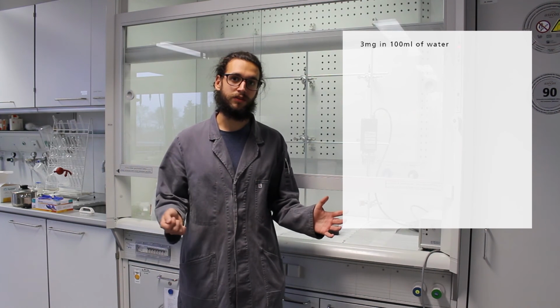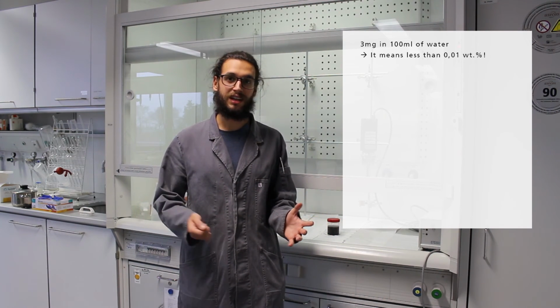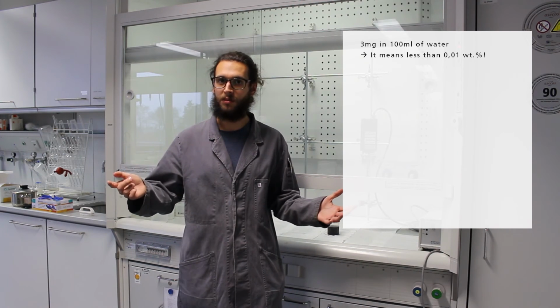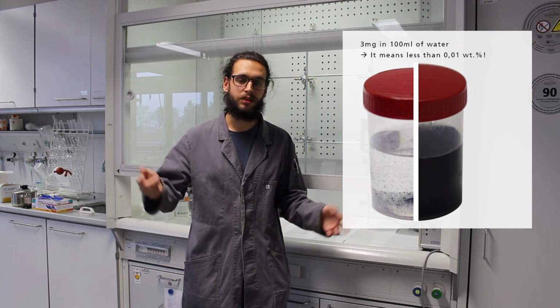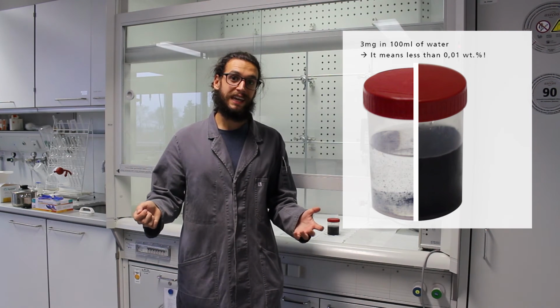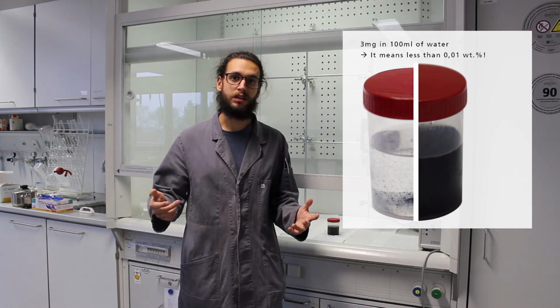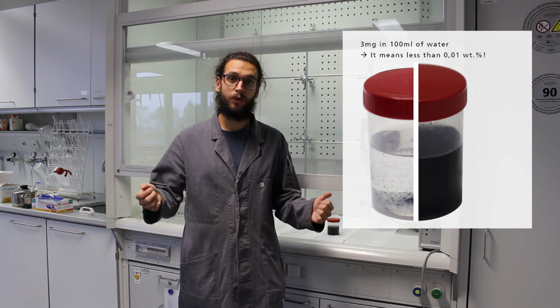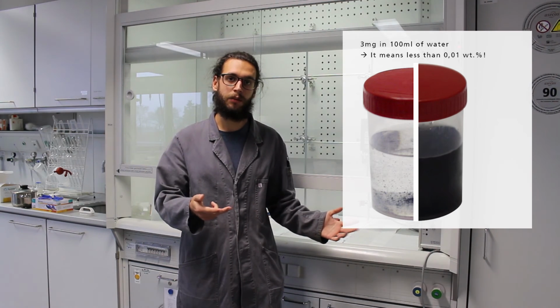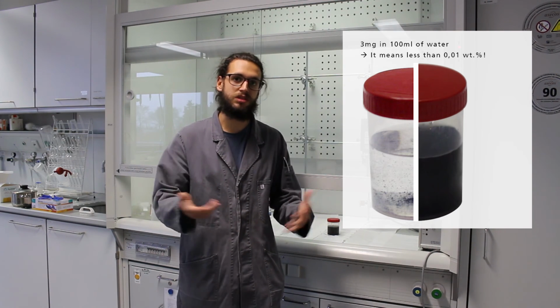Basically, if you noticed, I used a very, very small amount of nanotubes. It was less than 0.01 grams, maybe 0.003 grams, in about 100 milliliters of water. Anyways, you can see how black it became, and that in the beginning this was not the case.